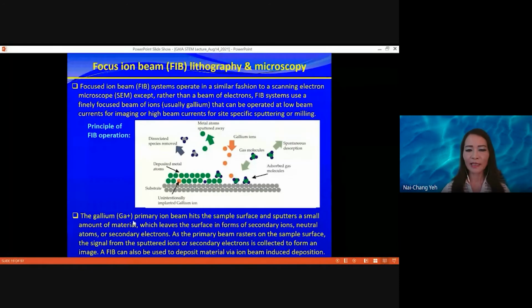So the gallium ion beam hits the sample surface and then sputters a small amount of material away and leaves the surface in the form of secondary ions, neutral atoms or secondary electrons. And then you can have detectors collecting the information. And so when you move your beam across, if you use high energy, you can remove a lot of material. And if you use low energy, you can do imaging. And also you can use the ions to deliberately deposit the ions into the material in the way you want.